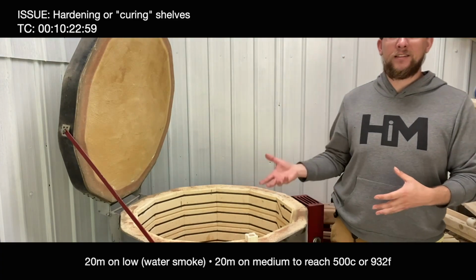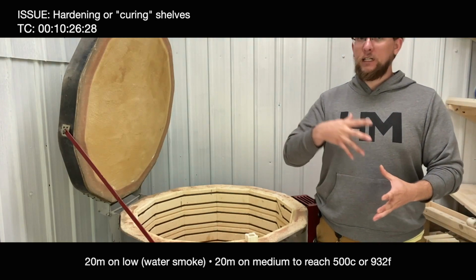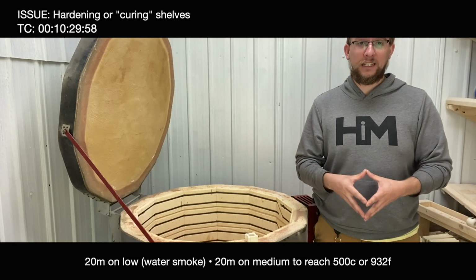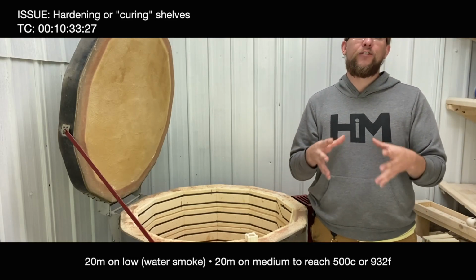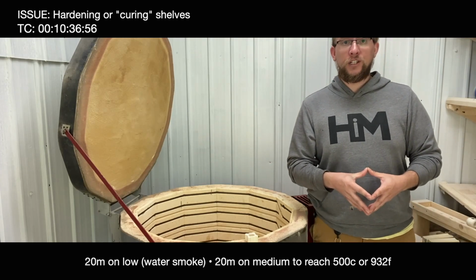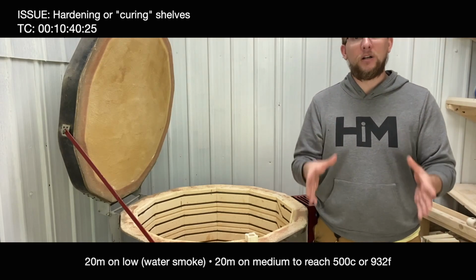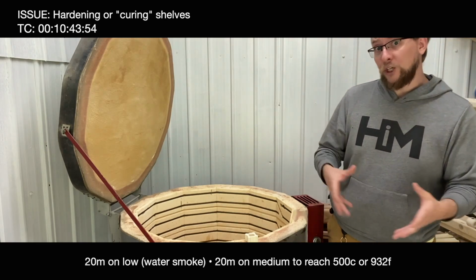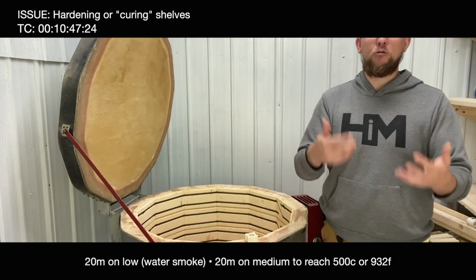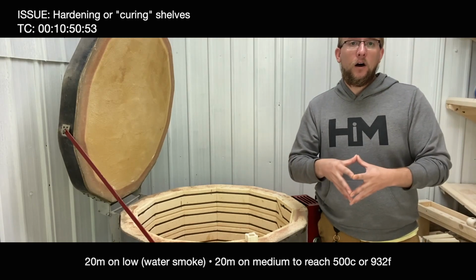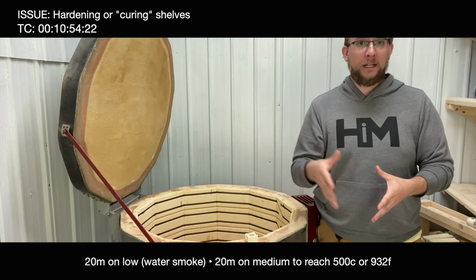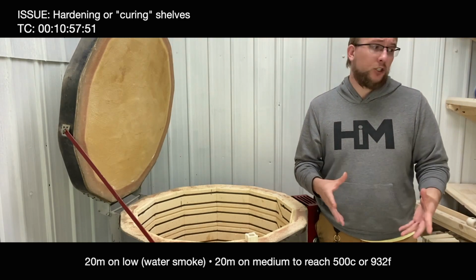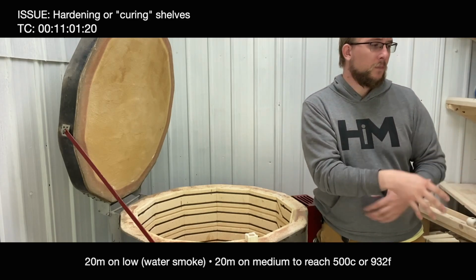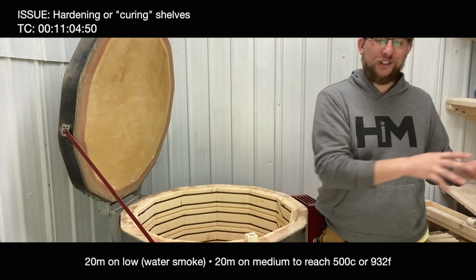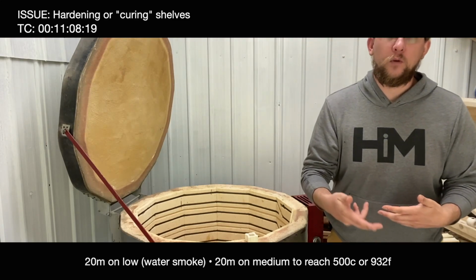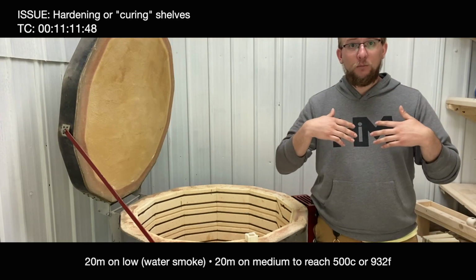So to cure these in the kiln by firing, you only need 20 minutes to reach a temperature of 500 degrees Celsius. That's roughly 932 degrees Fahrenheit, which is just under cone 022, which is the smallest cone that you can get. Therefore, really what you need is just to warm it up and then go to a high of medium if you're doing a manual, a medium, and let that rest on medium for 20 minutes. Now what I do, specifically if you do still have moisture on the shelf, is to allow a good 20-minute warm up on low, allow some of that moisture to escape.